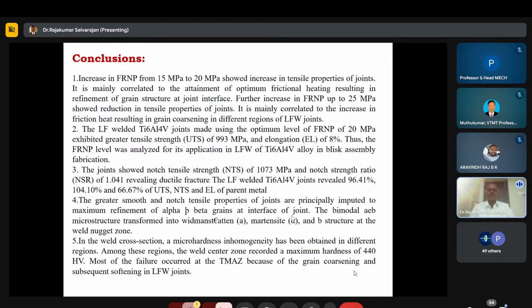So, conclusions from this linear friction welding work. We concluded that the titanium alloys made using an optimal level of 20 megapascal exhibited maximum tensile strength of 993 and elongation of 8%, and the joint showed the notch tensile strength of 1073 megapascal and the NSR of 1.041, revealing ductile fracture. The linear friction welded Ti64 joints revealed 96.41 and 104 and 66.67 of UTS percentage, and elongation parameters were also received.